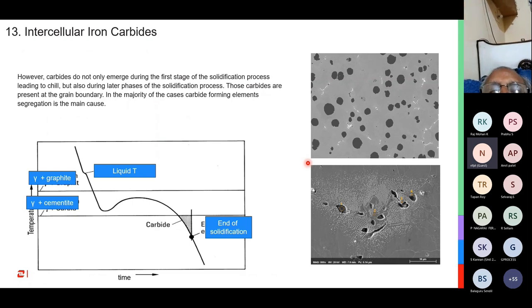The other aspect of it: we talked about the fast solidification and the initial primary carbides, but carbides do not emerge only during the fast solidification or the initial stage. In fact, in heavy section castings, which have a much slower solidification rate, these carbides can also be found towards the last to solidify, the end of freezing zone, towards the center or the core of the casting. And why does it happen there? Because of two major reasons. All these elements are low melting elements like manganese and chromium and vanadium, etc.